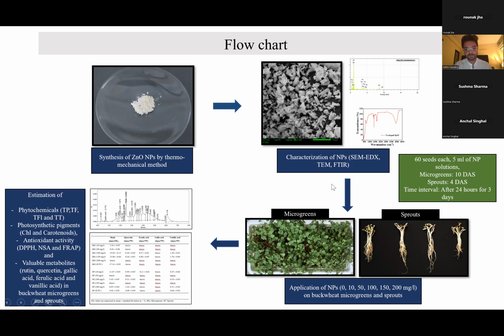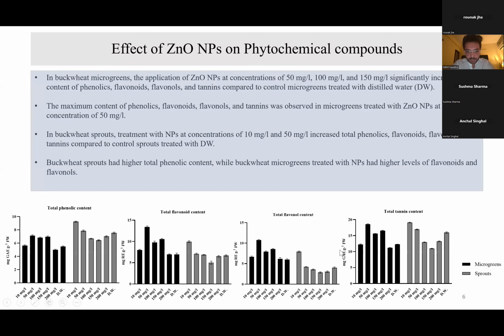All right. What kind of side effects did you observe on increasing the concentration? Now, on increasing the concentration, for example, I can show you that the content of flavonoids has also started to reduce. At a concentration of 10, the total flavonoid content in sprouts increased, whereas after that, the content reduced. So this is also one of the side effects of zinc oxide nanoparticles. So only at the optimum concentration that we have evaluated, we should be using zinc oxide nanoparticles for enhancing the content of bioactive compounds.